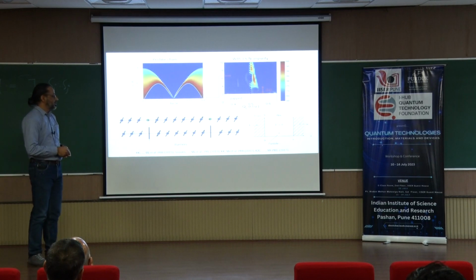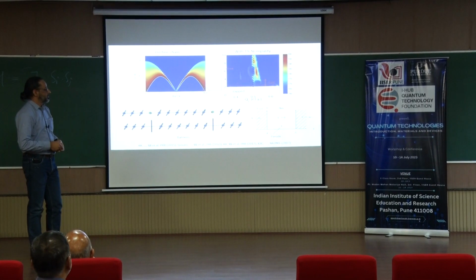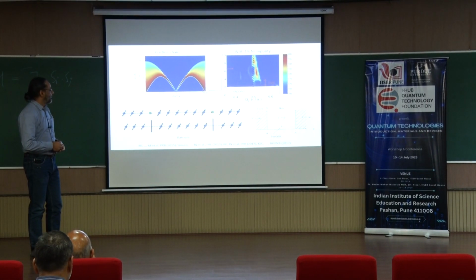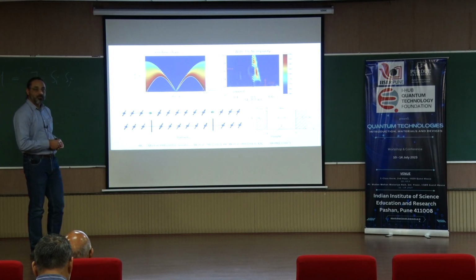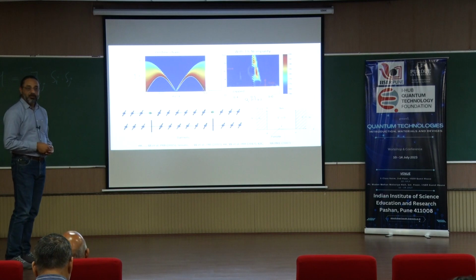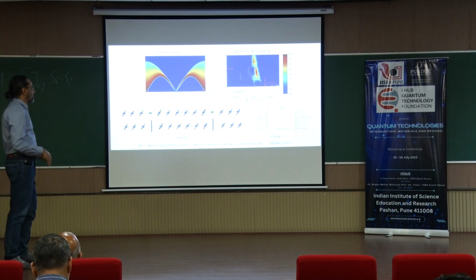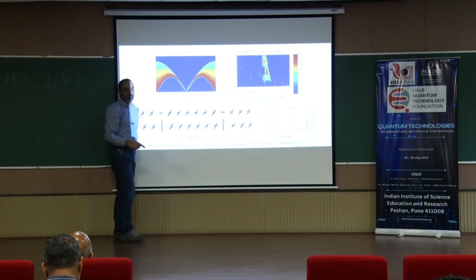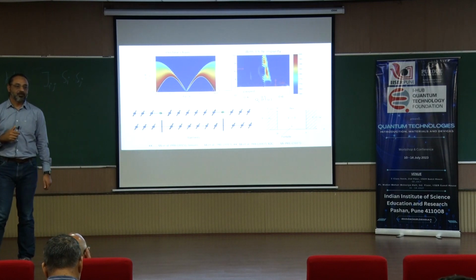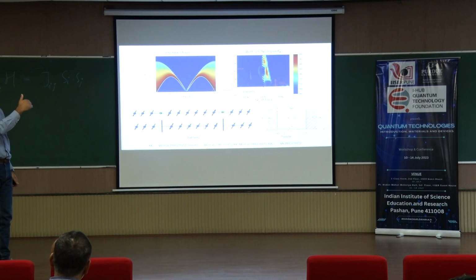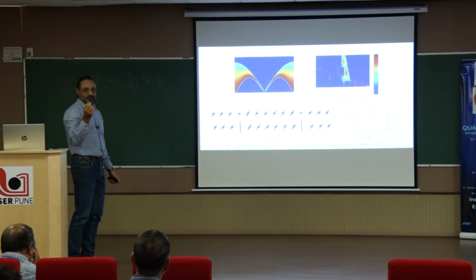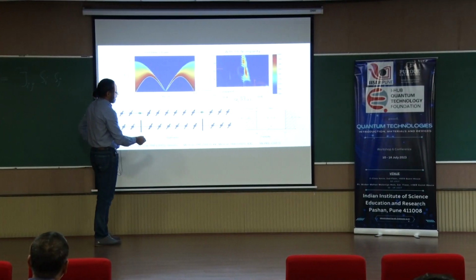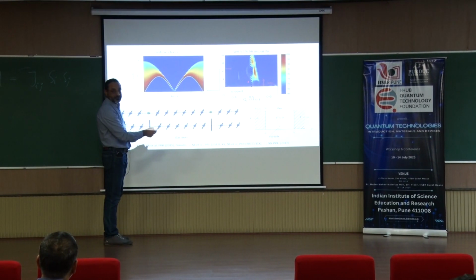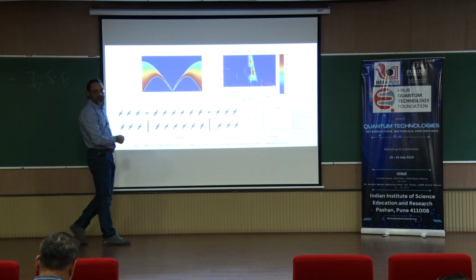This is very similar to a situation that you would encounter in an introductory quantum mechanics course, where you have V equal to 0 inside the box, which is akin to this region, and then you have these boundaries, which are analogous to these points where the chain is broken. So the spectrum, which was continuous, a continuum of states, we call a gapless spectrum, because the spinons get excited even at the slightest provocation. Now what you see is a gap. That gap has opened up, and it is a consequence of these scalar impurities.